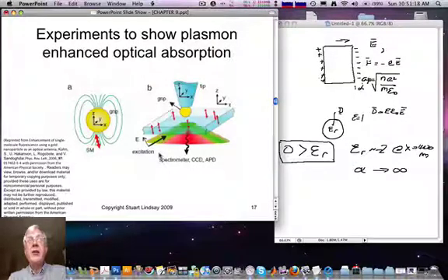This effect is controversial because the first order effect of placing a metal close to a fluorescing particle is to quench the fluorescence. When the particle is excited into a dipole excited state, rather than decaying by emitting fluorescence, the first mode of decay in the presence of a metal is to excite energy transfer into image dipoles in the metal that arise because of the large density of states within the metal. So metals usually quench fluorescence.